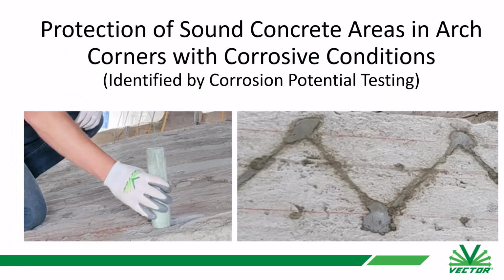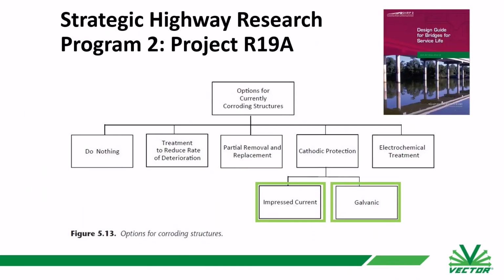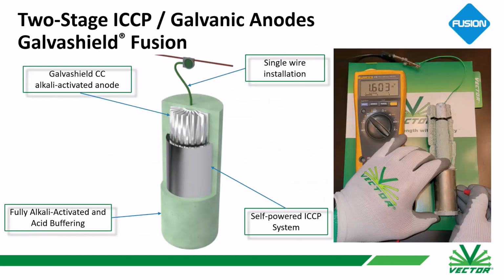Now, as part of this also, they did a full corrosion potential survey. So any of the areas where you didn't have the existing damage, but you were detecting active corrosion on the corners, they proactively installed these custom anodes. They call them two-stage anodes. So this is where the angle was, and you put a pattern of anodes on each side to provide proactive protection. Because as you saw previously, the amount of scaffolding and everything to get onto the structure is substantial. So to take care of not only the problems you see now, but the areas you can detect moving forward was the idea. And these anodes basically utilize a two-stage.